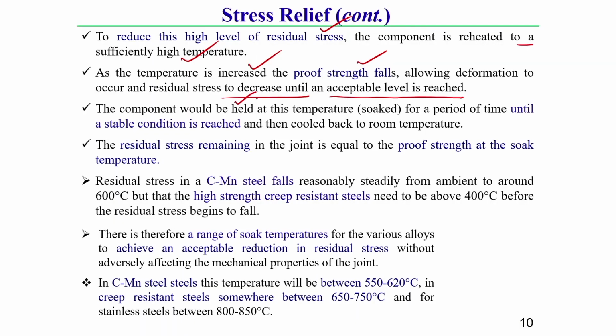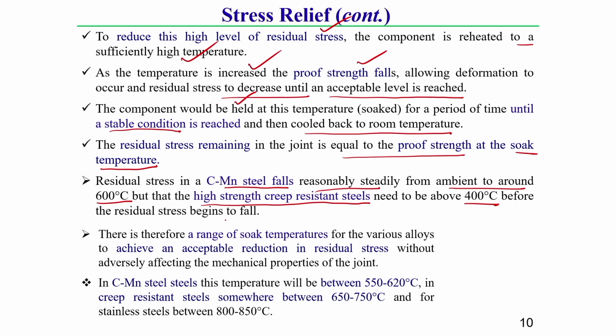Okay. The component would be held at this soaking temperature for a period of time until a stable condition is reached and then cooled back to room temperature. The residual stress remaining in the joint is equal to the proof strength at this soak temperature. This you should keep in mind. What does it mean? I will explain in detail here itself. So, residual stress in carbon manganese steel generally falls reasonably steadily from ambient temperature to 600 degree centigrade, but for high strength creep resistance steel, this residual stress starts to fall from 400 degree centigrade. What I am telling, understand?